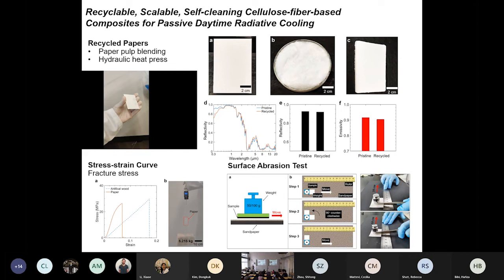After that, we also ran some mechanical tests, as I'm from the mechanical engineering department, not from the material department. So we need to run some mechanical tests to demonstrate this material is mechanically robust. So, stress strain curve, as you can see here, this material itself can be comparable to artificial wood. Not bad at all. Only for 3 layers of cooling paper, it could be comparable to wood.